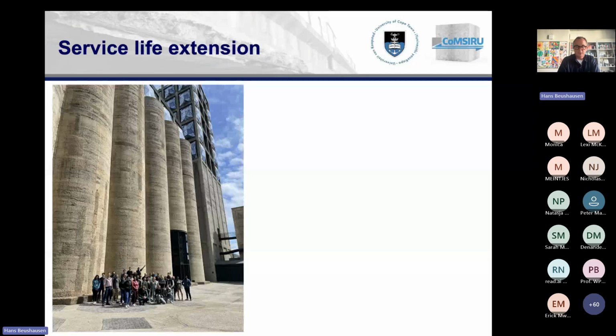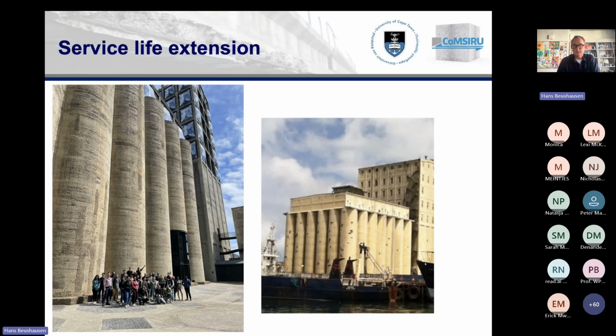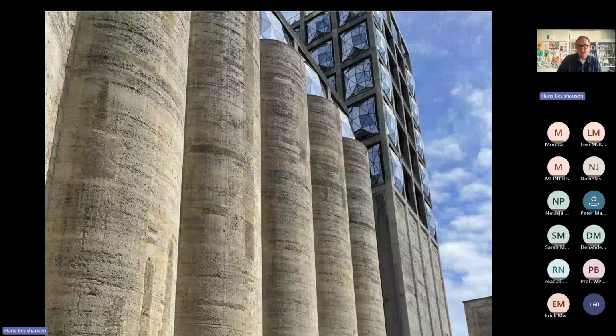And now, just one more point on durability. Looking at this structure here, this is the silo structure in Cape Town in the V&A Waterfront, which a few years ago looked like this. I always looked at the structure with great interest when I was having boat rides with my kids, and took this picture about 15 years ago. And all those black spots indicate delaminations on the structure, where reinforcement corrosion had led to chunks of concrete falling down, the steel was exposed and was corroding. And that structure was subsequently repaired about 10 years ago. And you can see all the patch repairs here on the surface.